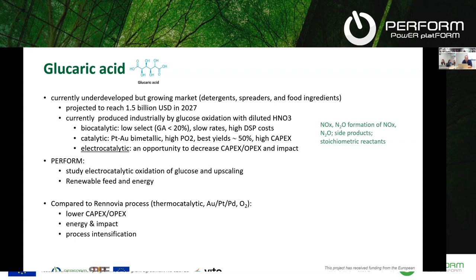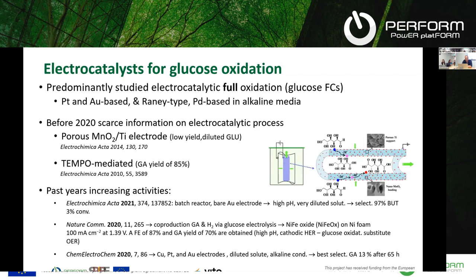There was an existing process patented by Rennovia, which was a thermocatalytic process based on gold, platinum, and palladium catalysts with supply of oxygen, which also indicated a lower capex and opex and energy and impact possibility. But we wanted to focus, of course, in this project on the electrocatalytic conversion. And therefore, we needed to find electrocatalysts, which was not very common at the time when we were starting the project. There was a lot of information on full oxidation of glucose in fuel cells, but very little on the actual electrocatalytic oxidation in electrolytic cells.